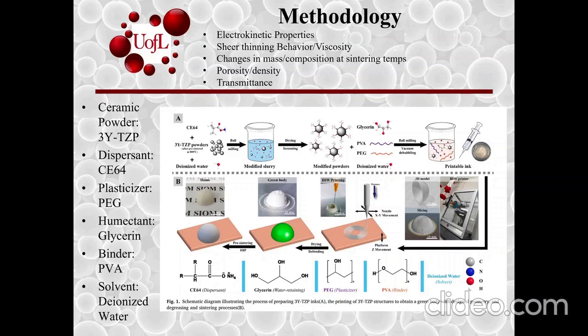PVA as a binder enhanced the bonding force between ceramic particles to ensure the ceramic body has a certain strength. PEG as a plasticizer softens the prepared ink, making ink more workable and fluid for pouring. And then by adding these two organic additives, a viscoelastic ceramic ink was prepared. And lastly, glycerin is added to the ink to avoid the loss of rheology of the already printed layer due to rapid evaporation of water, thus protecting the lower layer from damaging by the needle." So that kind of explains what all those additives are used for.